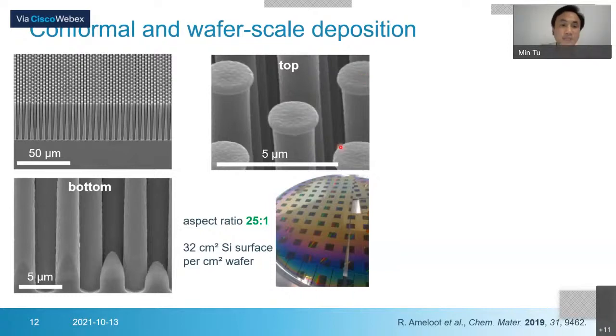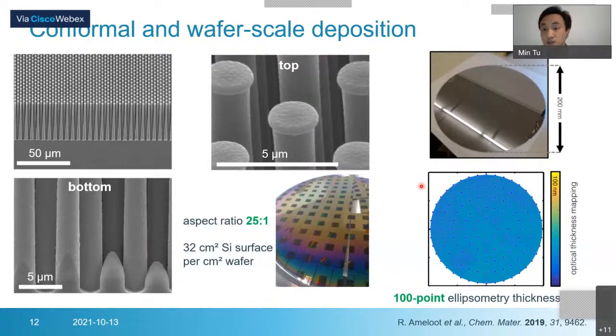Conformal deposition means it can grow not only on, for example, a flat surface, but can also deposit on high aspect ratio structures. Here, for instance, we have an aspect ratio of 25 to 1. You can see the pillars, which are silicon pillars. We can grow the MOF film over all the area, both the top and the bottom of these pillars. Another advantage is wafer scale deposition. They demonstrated the deposition on an 8-inch silicon wafer, and by 100-point ellipsometry measurements you can see the homogeneous MOF film coating on this large wafer. This is a demonstration of ZIF-8, one typical MOF.